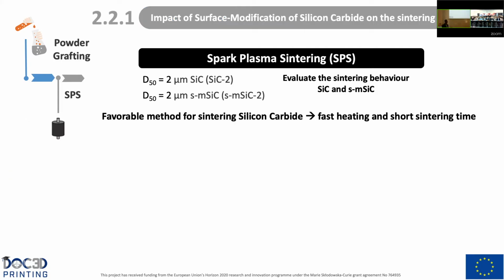So now it's time to study the impact of this surface modification on the sintering behavior of the powder. For this, we are going to use 2 different powders, 2 micrometer silicon carbide powder as received and after the surface modification, and we are going to evaluate the sintering behavior. Here we are using spark plasma sintering because this is a favorable method for sintering silicon carbide, as reported in literature, and it provides fast heating and a short sintering.